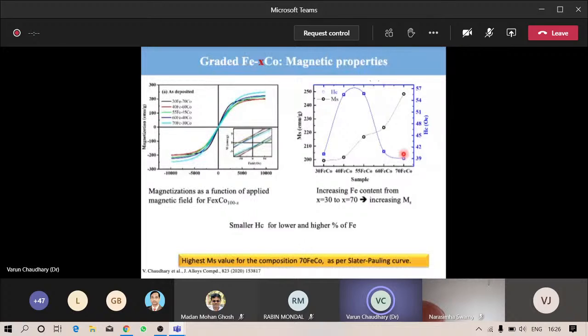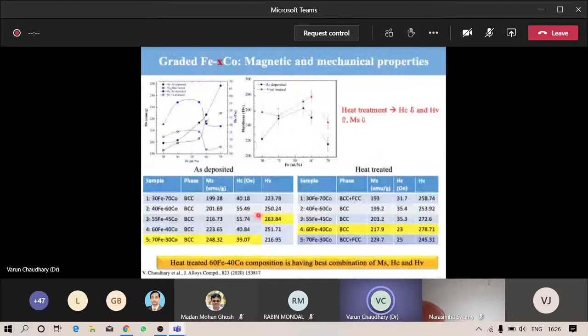What is our requirement? Then we measured the mechanical property. The mechanical property for that particular composition is not good, but it is good for another composition. Then we annealed all these samples and found a significant decrease in the coercivity and some improvement in the mechanical property, basically in hardness. Finally, we identified a composition with good saturation magnetization, low coercivity, and high hardness. So we have found a composition with the best combination of saturation magnetization, coercivity, and hardness.